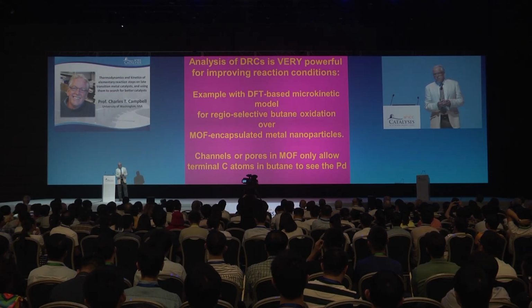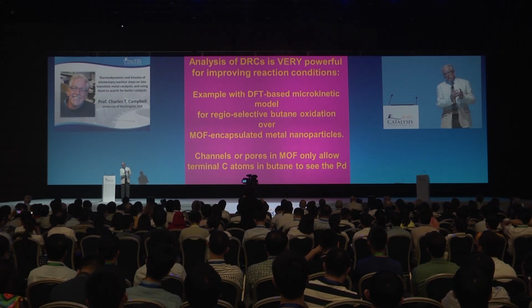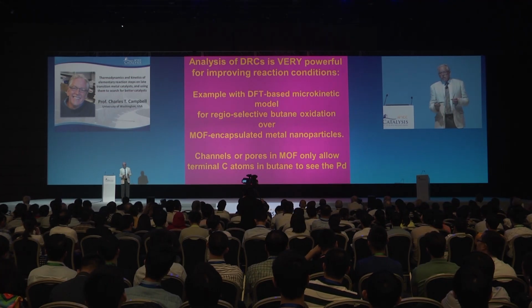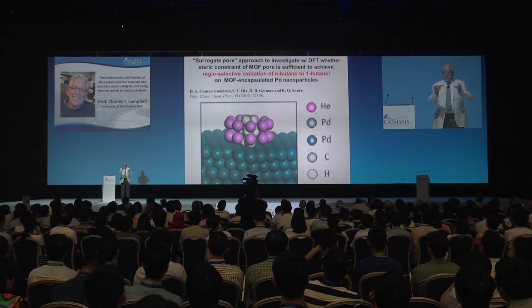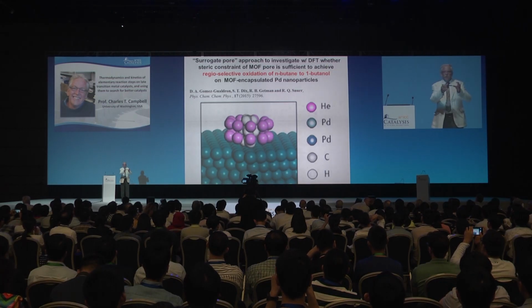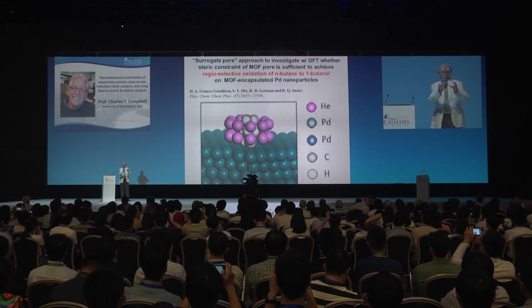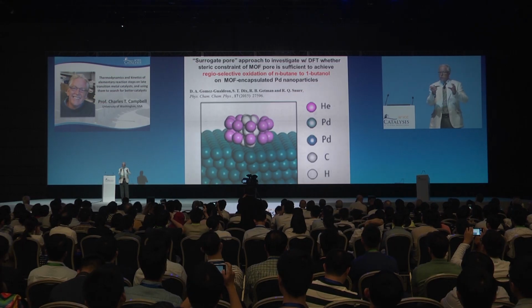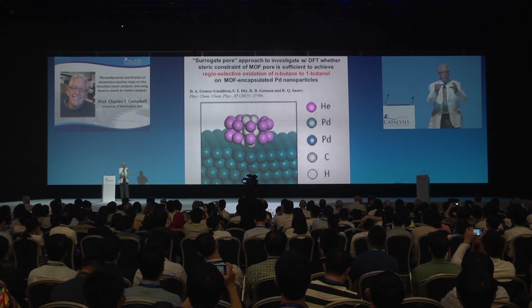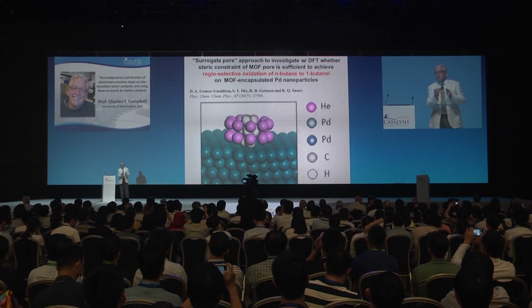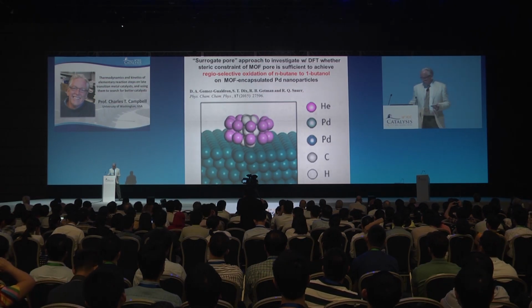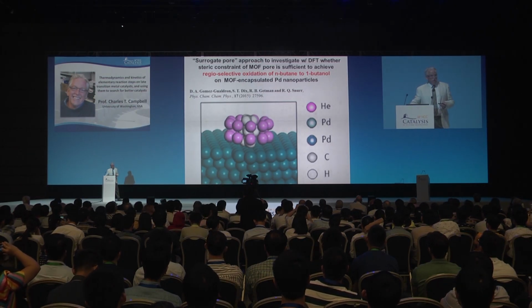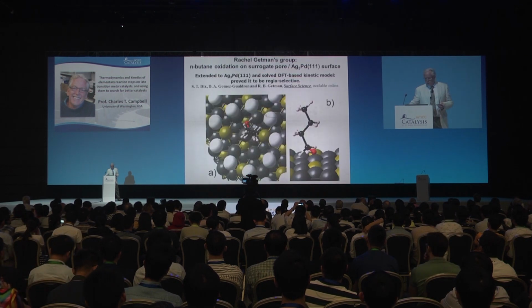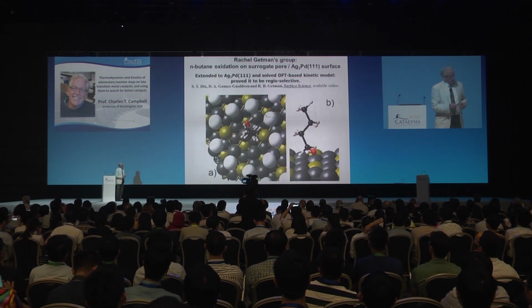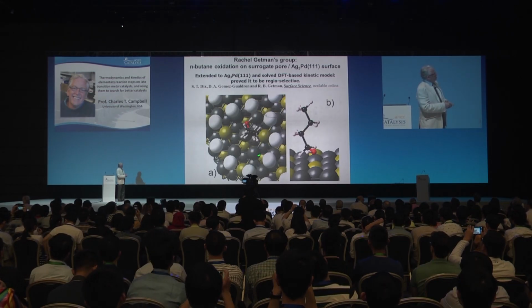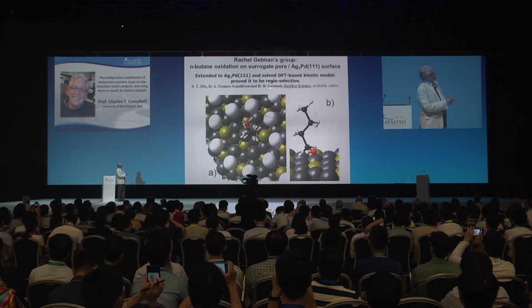And so it's kind of like a nanoparticle or a cluster in a zeolite. When the reactant comes along, it has to line up along the pores of the metal organic framework. So, for example, in this case, for butane, the palladium can only be accessed from the end carbon atom of the butane molecule. So it causes regioselective oxidation.